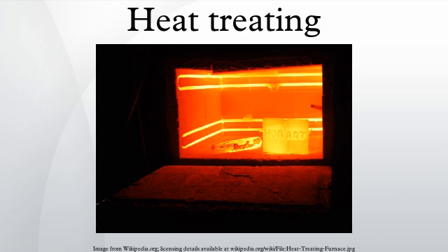Cold and cryogenic treatments are typically done immediately after quenching, before any tempering, and will increase the hardness, wear resistance, and reduce the internal stresses in the metal but, because it is really an extension of the quenching process, it may increase the chances of cracking during the procedure. The process is often used for tools, bearings, or other items that require good wear resistance. However, it is usually only effective in high-carbon or high-alloy steels in which more than 10% austenite is retained after quenching. Specification: usually the end condition is specified instead of the process used in heat treatment.